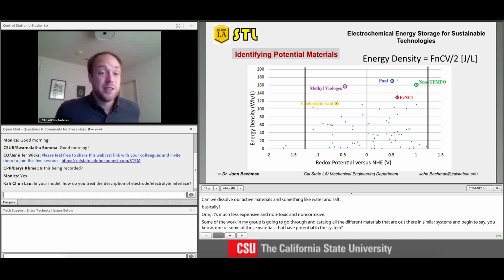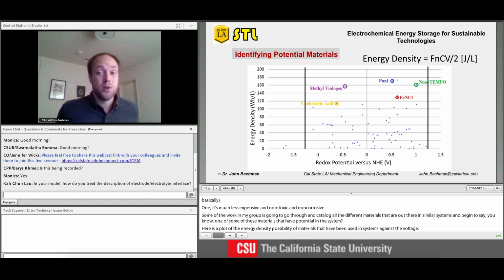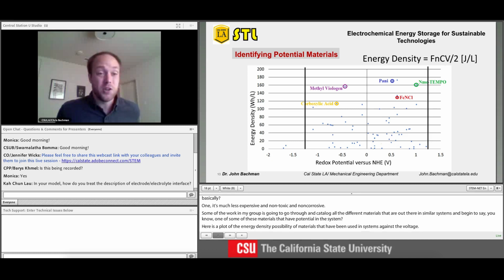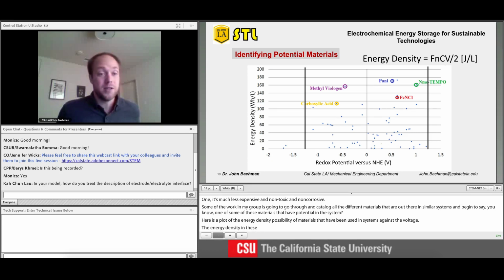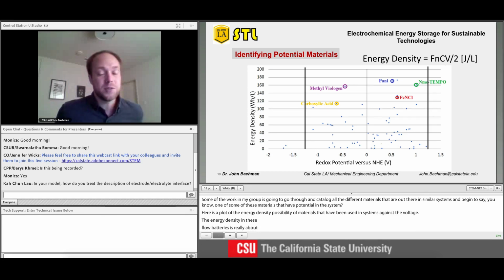And the energy density in these flow batteries is really about, up in the top right corner, the F and the n are constants, and then you have concentration, C, and voltage. So you want something where you can dissolve a lot of it in the tanks, because that'll increase how much energy is in the tank. And you want to have a large voltage difference.